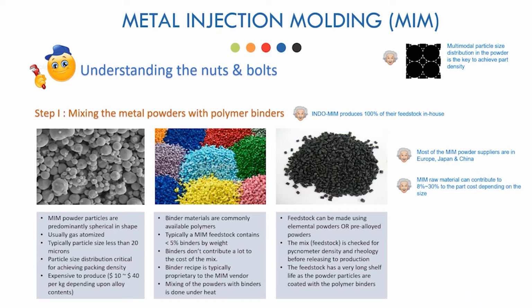MIM powder costs are among the main cost drivers in a MIM component. Hence, larger size components don't make good MIM candidates. Normally, components less than 100 grams are economically viable through the MIM process. At Indomim, we find the 20 to 30 gram weight range the sweet spot.